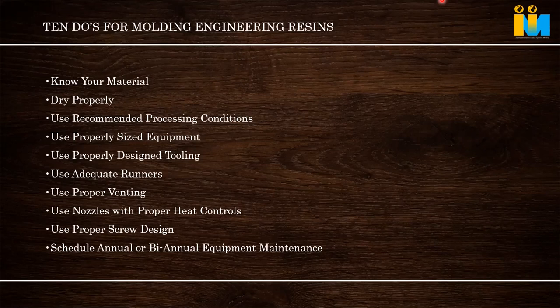And use proper air venting. Air venting is based on the raw material. We have discussed for nylon 0.02 to 0.03. For PC, higher viscosity, maybe you take 0.05, 0.06 also. Ultem also we can go like that. Proper values will also be covered in the data sheet of the raw material. Please refer to that. If not, ask the raw material people and give a vent.